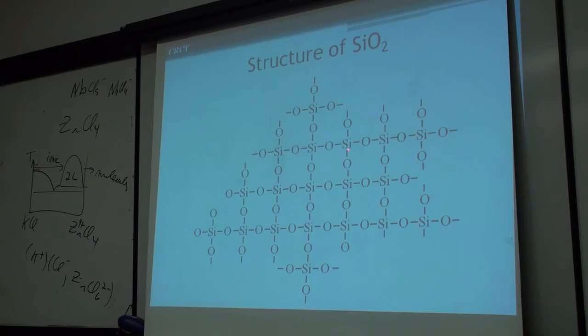You can imagine the diamond silicon, metallic silicon, forms a diamond lattice. And at least in the cristobalite structure, you just put the silicons on the diamond lattice, but you put oxygens between them. You can imagine that this is not ionic, because these things are not mobile. These are covalent bonds. It's extremely viscous, because covalent bonds are directional. Ionic bonds are not directional. The strength of an ionic bond just depends upon the distance between the 2 ions. But here it depends very much on the angle.